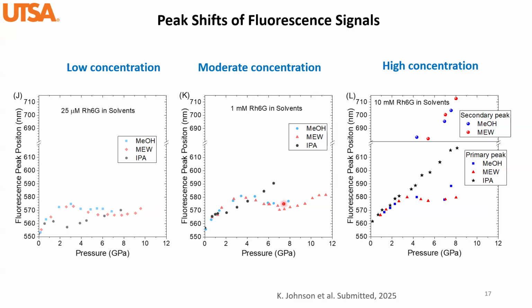And this, combined with the fact that the red shift is due to the HOMO-LUMO gap of the molecule being reduced, but this blue shift, we think it's because of the interaction between the dye molecule and the solvents. Because the existence of this blue shift is affected by which type of solvent you're using, and also how concentrated your molecule is. So that indicates solute-solvent interaction.